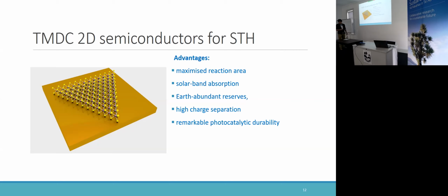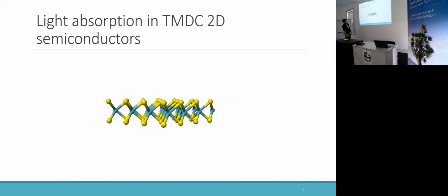And of course, it has its own shortcoming, and that is low light absorption. For 1 monolayer of the 2D TMDC, the absorption is 10%. It's already very high at such a thin thickness, but the problem is it's too thin. So when a beam of light shines on the structure, it passes the monolayer once, so 10% of the light can be absorbed.